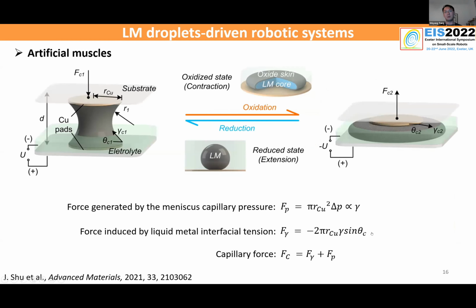Using the oxidation and reduction mechanism, we next created a liquid metal enabled artificial muscle. Basically, we have a liquid metal bridge connecting 2 substrates, and the bridge is half immersed in the electrolyte. In this system, we have 2 dominant forces. The first is capillary pressure, which is a function of the surface tension of the liquid metal, and the liquid metal interfacial tension also contributes to the overall capillary force. The interfacial tension force is always trying to pull these two substrates towards each other. That's the reason why it has a negative sign.